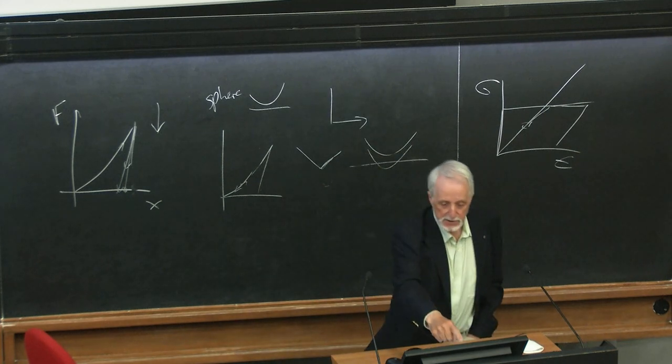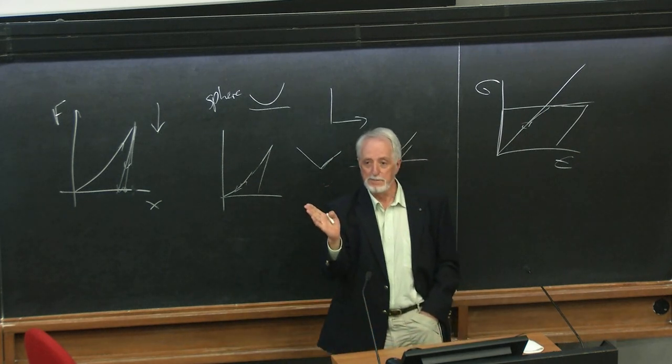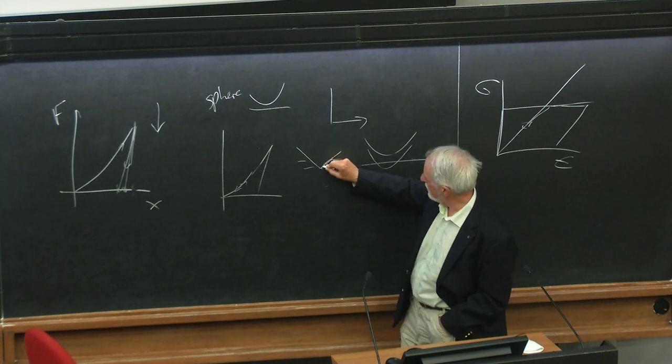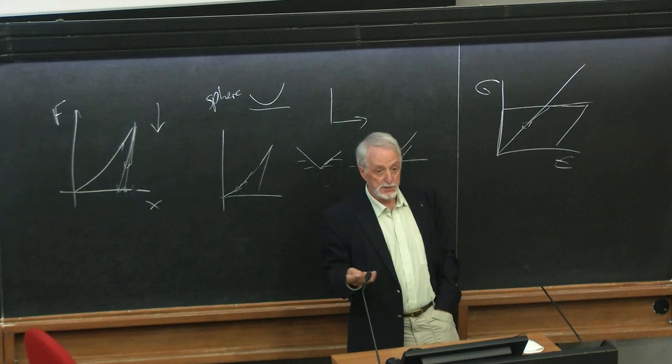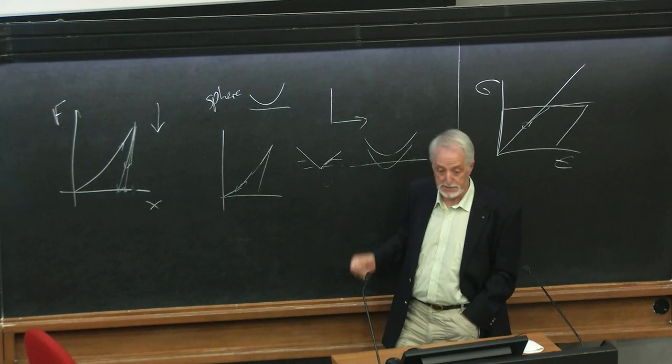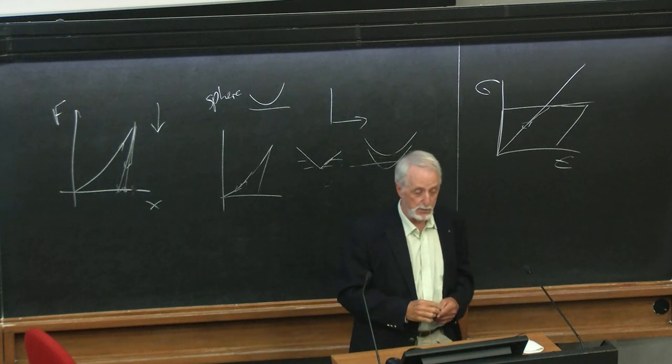It's even better than that. You see all the curves sit almost on top of each other, irrespective of the size of the hole you make. That, okay? And that's what you'd expect with a self-similar system, which is what you've got with a tip like that, okay? So this all seems to work quite nicely.